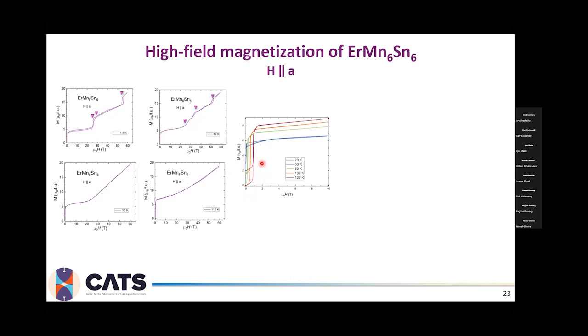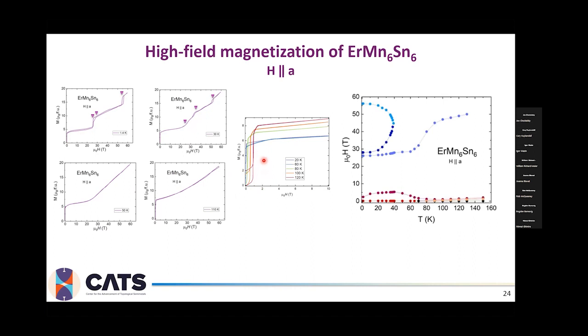temperatures. So by making many of these curves, this is how the phase diagram looks for the magnetic field applied along the A direction. These transitions, which were merging together, actually formed that bubble, which was predicted in the theoretical calculation. We can also see that above 91 Kelvin, most of the interesting things happening are only in the low field.